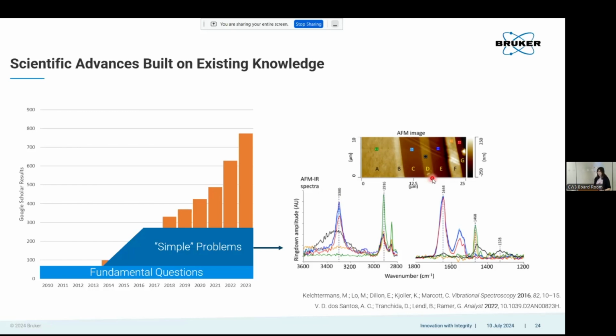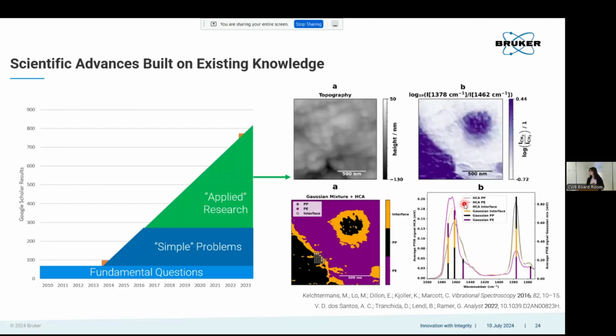But then you get into, based on this knowledge, based on what we're seeing here, which is that relationship between FTIR and AFM-IR, you start to do these applied research problems. And so these get into the much more complicated analysis. How can we learn much more about the material itself? So this is a post-consumer recycled plastic. This is a material where they have taken your PET bottle, they've broken it down, they've remade it, and then they want to characterize it. And when you look at the topography, you don't see anything, right? It looks basically homogeneous. But when you start to look at the infrared intensity, you can see variations in two unique domains here.